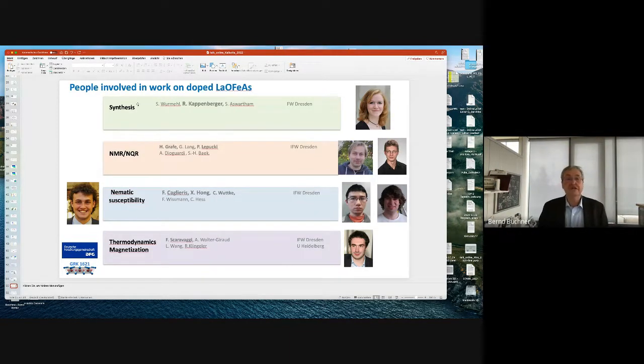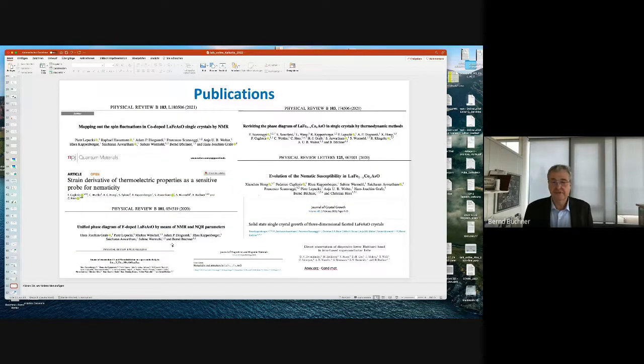We can synthesize samples, we can do NMR measurements, we can measure these nematic susceptibilities, these strain-dependent transport measurements. The photoemission, which I have not shown here because it was not done on these systems yet, and we can do the magnetization and thermodynamics. And if you want to read more on that, this is a collection of the papers which appeared in the last years, dealing with just this series of samples which have been synthesized for the first time.